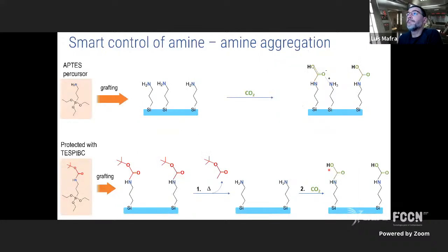This is the question. So to try to disentangle this problem, apart from the conventional grafting, where you just graft amine and then you adsorb CO2 and that's it, we try to protect these amines prior to grafting. Then we graft them, and because it's very bulky, they will be spaced apart. So the idea here is to control the amine aggregation, to put them further apart as much as possible to quench amine interactions, these strong hydrogen bonds. So at least we want to minimize them.